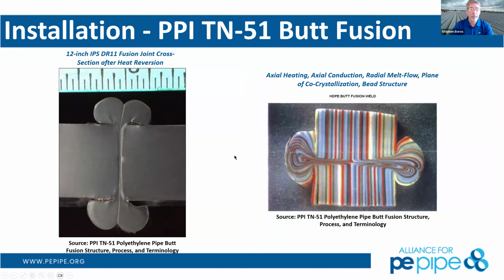This is what happens during a butt fusion joint. So you can see here, this is the wall thickness. You can see the two ends were brought together, and it talks about the different aspects of it. So you get your external rollback bead, and you get your internal rollback bead from the molten material that was squeezed out. And it gives you different flow profiles. You can see on the picture to the right here, which was a very unique piece of pipe that was made. I'm not sure if it was made on purpose or by accident, but it certainly gave a good graphic for this example. You can see that when the pipe ends are brought together in this fashion, the melt is extruded out this way and this way, and that interface is right here in the middle, where you get what we call a co-crystallization zone, where you get that real entanglement that gives you a fully strong joint. It's not just touching together or mechanical adhesion. This is a true intermolecular crystallization area that gives you a 100% strong joint.